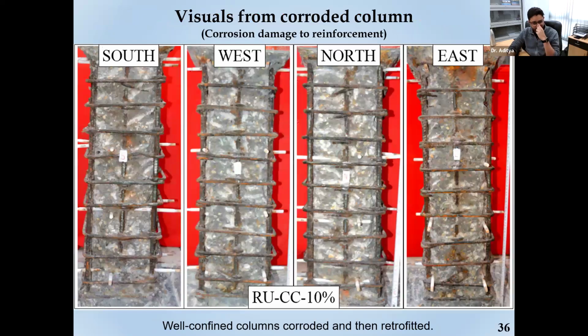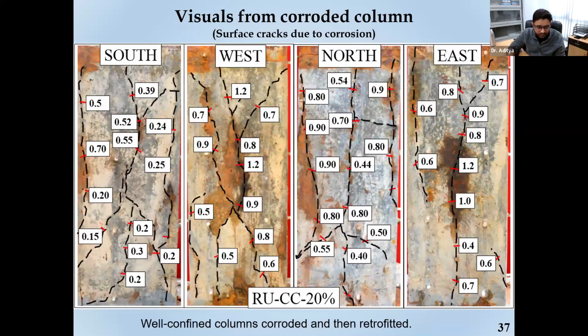These are some of the visuals from experiments. You can see the corroded columns. These are 10% corroded columns. This is a 20% corroded column at the surface. You can see the width of the cracks in mm, 0.7 mm, 0.4. So it's basically randomly distributed all across the test length, which is 800 mm.